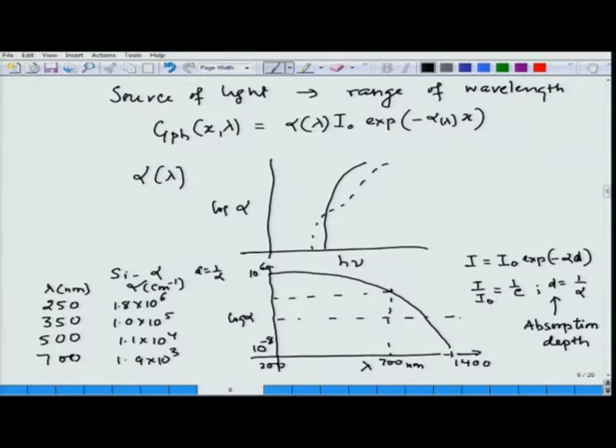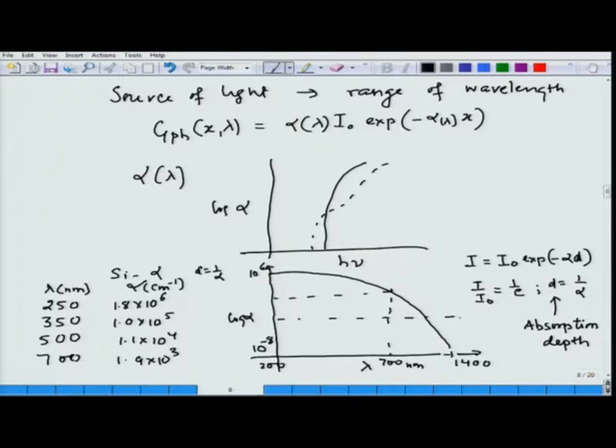So, a question that one could ask is how thick should the solar cell be if you want to absorb as much light as possible. Now, the answer to that question is that it should be as thick as possible, because typically the solar spectrum peaks in the visible range at around 400-500 nanometer, and a lot of it is beyond the silicon band edge. But if you take any particular wavelength, you need smaller thickness to absorb lower wavelengths, but as you go towards larger wavelength, you need much thicker silicon substrate, and obviously if you want to absorb all of it, you need a much larger silicon thickness to absorb most of the sunlight.